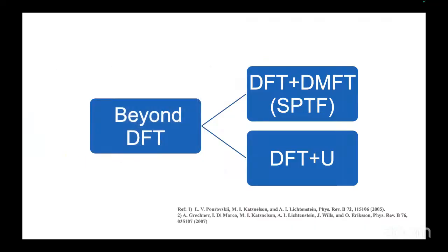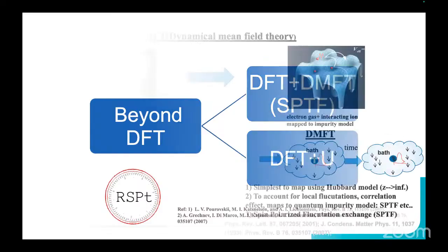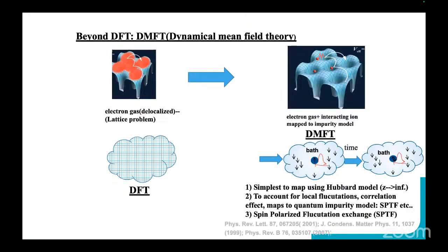So we went beyond DFT. I did DFT plus DMFT using SPTF as a solver, and DFT plus U to account for both static and dynamic correlation, as implemented in RSPT. A brief summary of how we go from DFT to DMFT: we go from a delocalized electron gas picture to interacting electrons, where we can take into account the fluctuations. For this, we map onto an impurity model, and I have used SPTF as an impurity solver, a spin polarized fluctuation exchange solver. It is a perturbative solver, an extension of FLEX with the T matrix fluctuation, taking into account all kinds of fluctuation in the system.